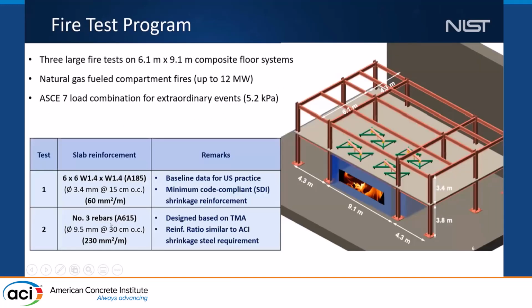The NIST fire test program consists of 3 large fire experiments conducted on this 6.1 meter by 9.1 meter composite floor situated within this 2-story test frame. For fire conditions, we use natural gas burners, with which we can create compartment fires up to a heat release rate of 12 megawatts. And also the test floor slab is loaded using hydraulic actuators, with values conforming to the ASCE 7 load combination for extraordinary events, 1.2D plus 0.5 live.